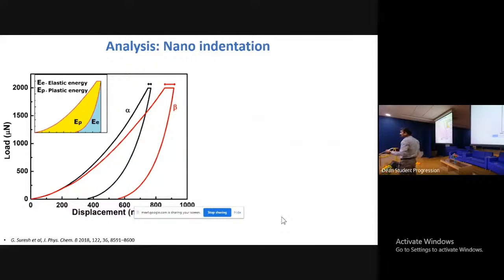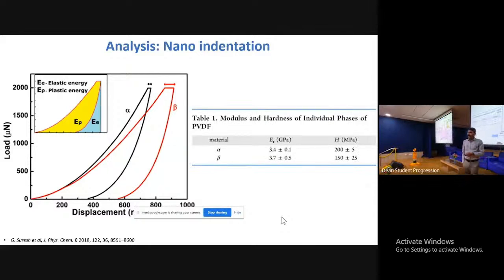What we did is, two different phases were prepared. We tried to understand the nature of each, what its elastic energy and what its plastic energy is. Not really too much into that. What you can understand from this is that the alpha phase has this much hardness, whereas the beta phase has lesser hardness. In fact, this is shown for the first time: the beta phase is going to be softer than the alpha phase.